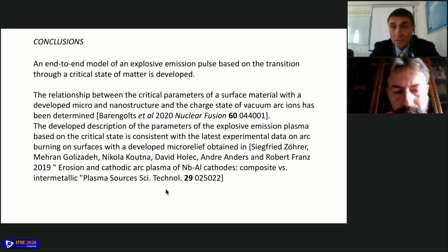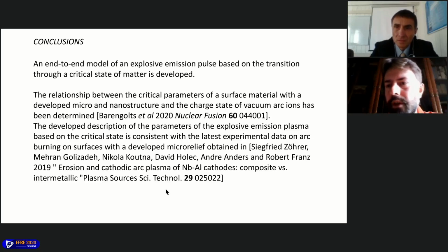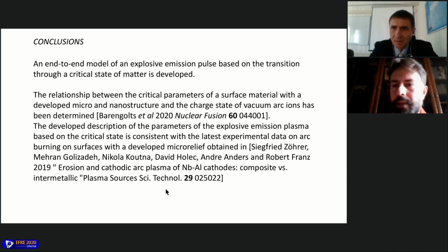There's a difference between, let's say, high voltage discharge with the vacuum breakdown or vacuum spark with high voltage, and low voltage arc discharge. So there may be a difference between this kind of discharge, in fact. We have shown previously that for large enough energy flux to the surface, we can drive explosive processes without any non-homogeneity at a flat surface. So then, formally, we do not need any non-homogeneity on the surface. But here, it was interesting to analyze some threshold low energy flux conditions. So it's related to the vacuum arc, first of all, and basically for clean metals.